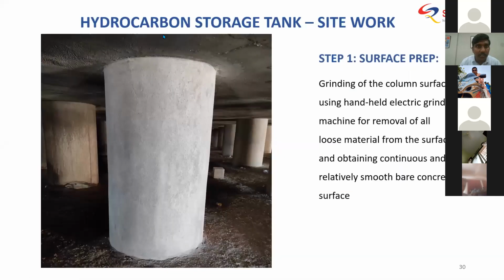This was the column, and you have to grind and finish the surface so that only the bare concrete is visible. This is after the spalling repair. You can see a little bit of black patch here, which was smoothened previously. The client themselves did some gunniting for this particular column. We usually use the structural putty, but ultimately it's a good hard concrete surface.